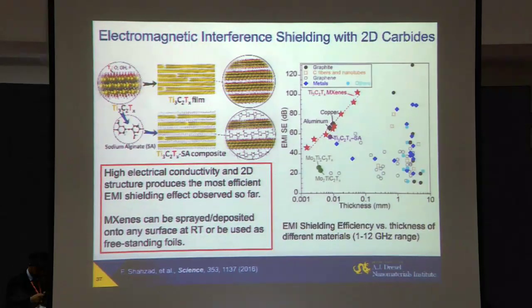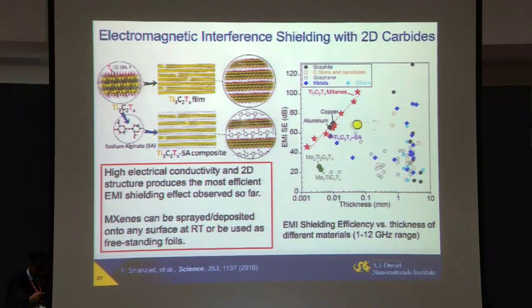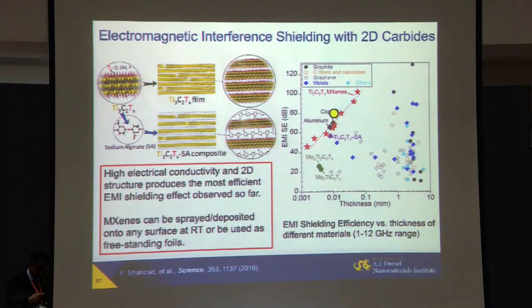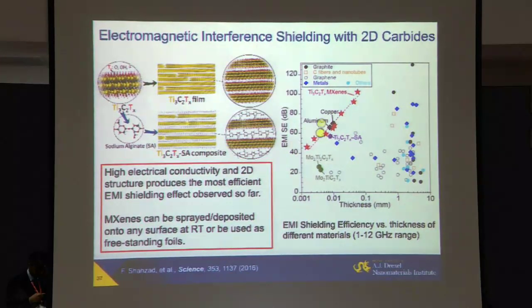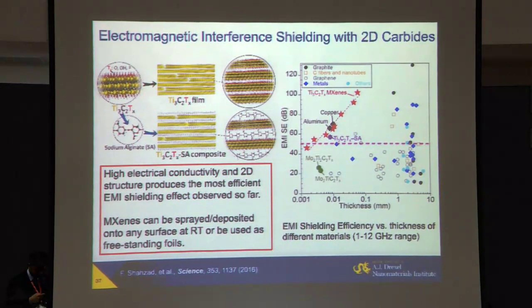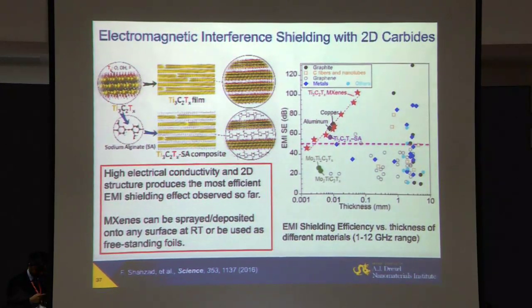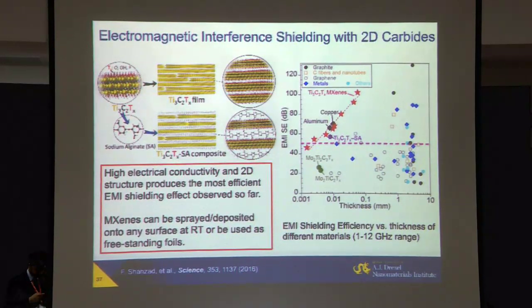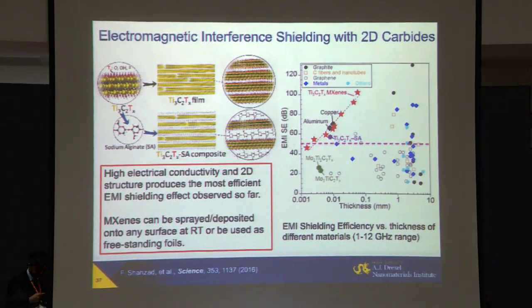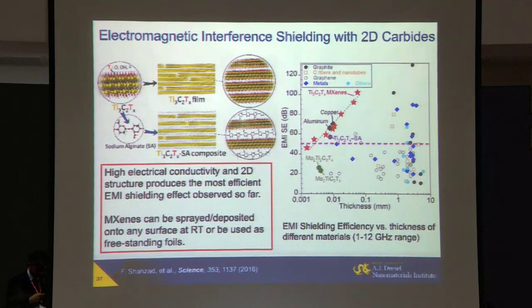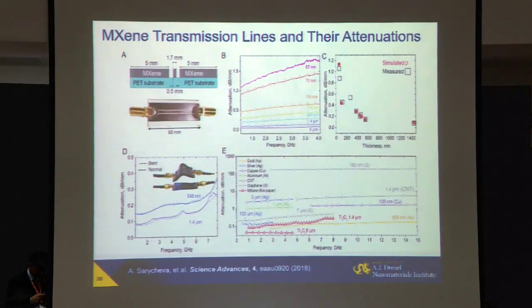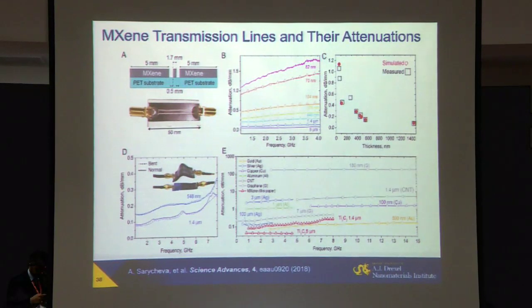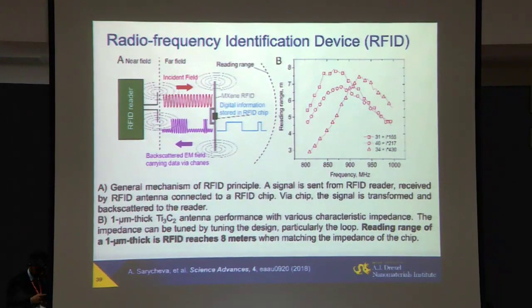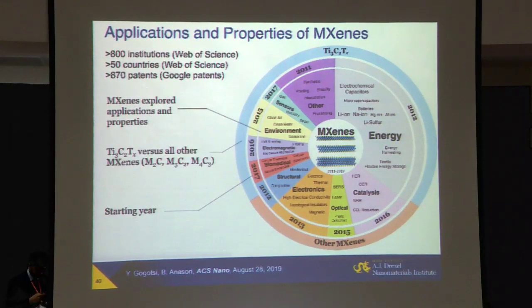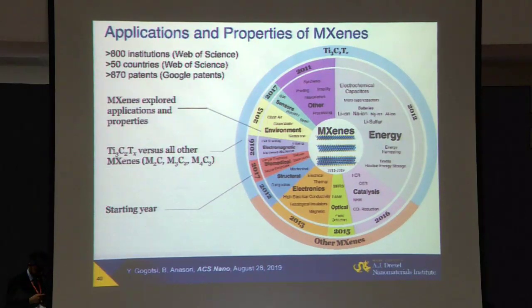So far, it is probably the best electromagnetic shielding material available. Now we pushed its protecting properties above copper, but what is important, for achieving about 50 decibel, we can just have a 1 micron film of material instead of metal foils with about 10 to 20 micron thickness that you use nowadays. And for wearable electronics and Internet of Things devices, that is important. We can make printable antennas for 5G internet, RFID tags with much larger interaction distance. So there are many, many applications, and this diagram shows that.